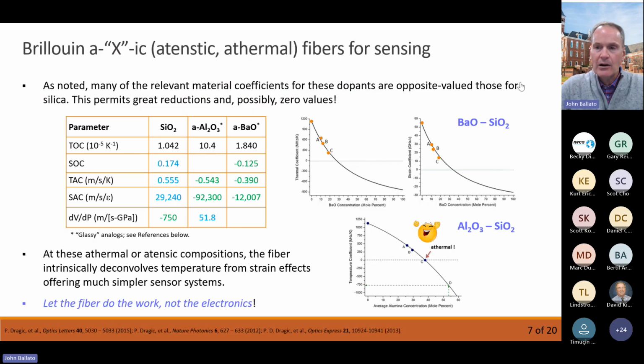So this is where we begin to use those positive and negative effects, right? So you have TOC, which is thermo-optic, SOC, which is strain-optic, and then you have the strain-optic, thermo-optic, strain-acoustic, thermo-acoustic properties. And again, with certain dopants like alumina or baria, when you mix them into silica, when you have an aluminosilicate or a barium silicate, you can offset these positives and negatives.